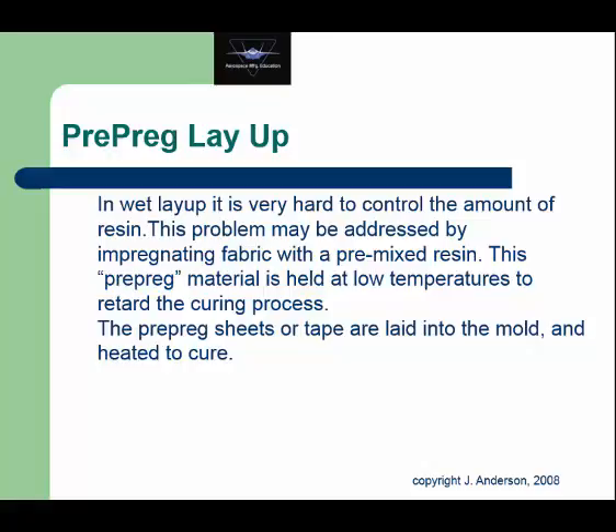So now we have these sheets that have both the fibers and the resin in a very controlled volume of resin, and we can put these in a refrigerator and keep them for a certain period of time. They all have a shelf life because the cross-linking goes forward even at lower temperatures. So we put these in a refrigerator, and then we pull them out as we need them, and we can lay those in place. So now we have resin and the fibers in the mold when we lay it up. The interesting thing about this is that we can get typically, I guess, around 60% volume of fiber as versus matrix in our material, and we can't even approach that using the wet layup method.